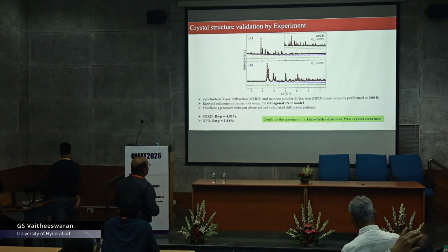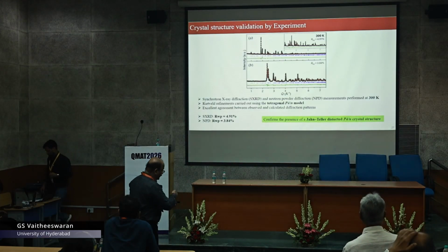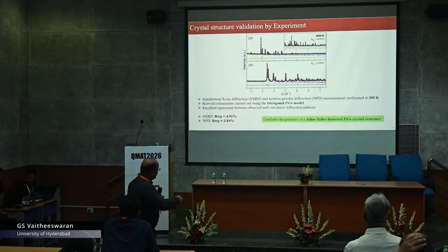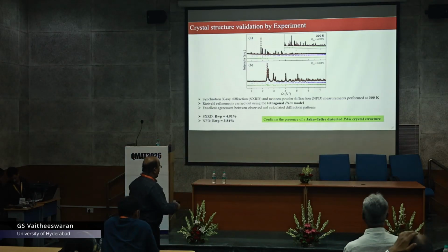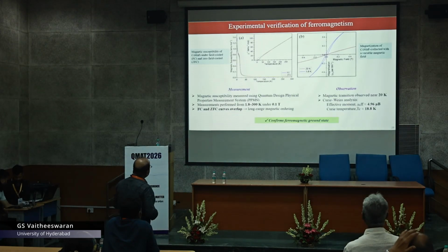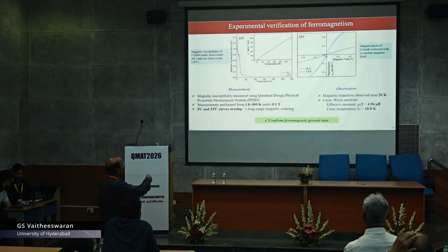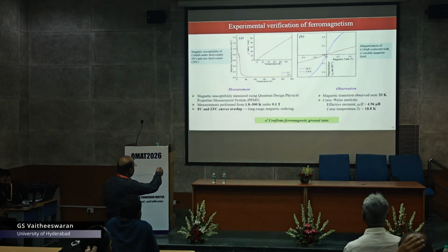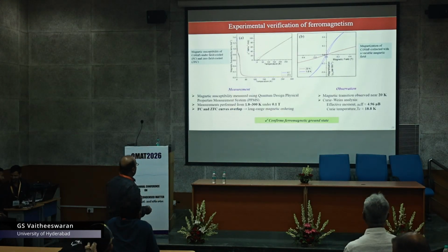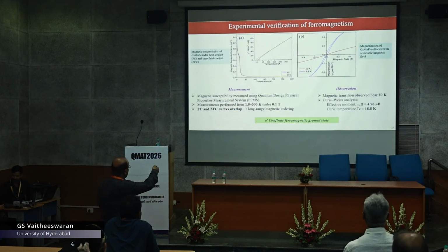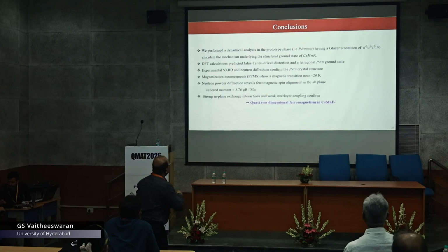So that's what they say, and then they confirm the presence of the Jahn-Teller distortion, which is a mandate for this particular system in the P4 bar N crystal structure. Yeah, so it is a weak ferromagnet. So the hysteresis, these are the experimental measurements done by them, and maybe as a function of field this can be improved. I don't know much about this, but they confirmed the ferromagnetic ground state of this system.